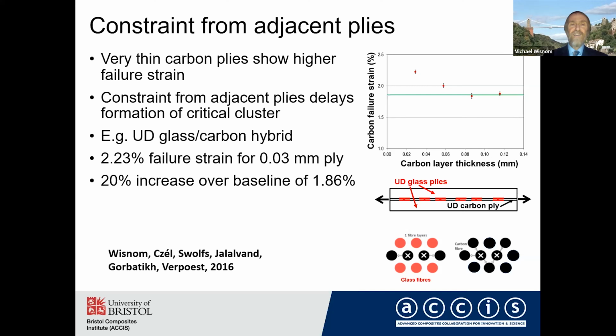Quite a large effect. And the reason for this, we believe, is because of the constraint on forming the critical clusters of fiber breaks, which can form the failure.